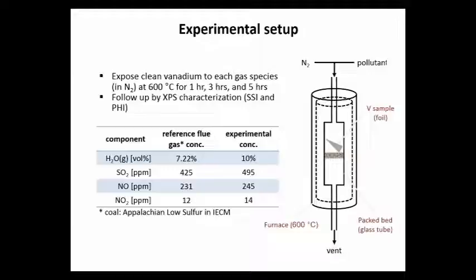So what that means is we have argon that we can use to sputter the surface and take some of the first few molecular layers off the surface. What if we pull this out of our system, our reactor? It had sulfur on the surface in the reactor. We pull it out and it's exposed to oxygen. And then the oxygen gets on the surface, and that's why we don't see sulfur, because XPS is a surface sensitive instrument. So we want to make sure that we're seeing what we think we're seeing.